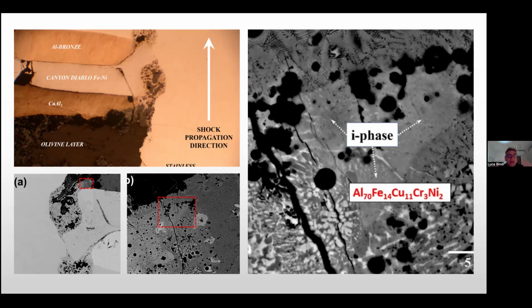And to our surprise, you can see that we produced some blobs here, originating from the melting of the metallic projectile. But of course, we were interested in the interface between the silicate and the copper-aluminum alloys. So if you look at this metallographic image and rotate it 180 degrees, and you look at the scanning electron microscopy image here on the bottom left, you are at the contact between copper-aluminum and the silicate.